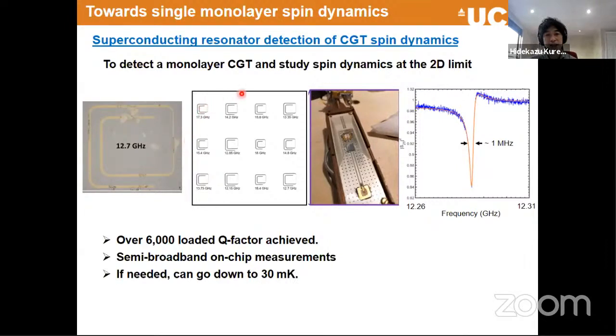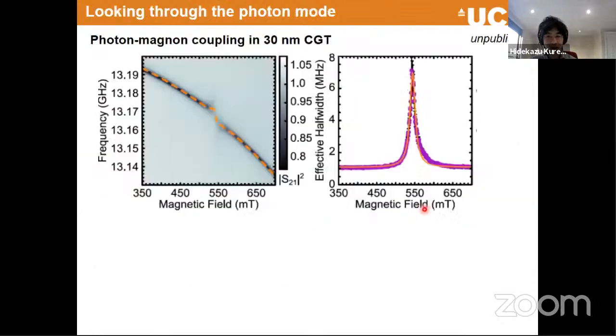Then we make it on the substrate and connect it to a transmission line, and then we can see the resonance. The loaded resonance, or Q factor, is about 6,000, so the line width is about a few megahertz at a resonance of around 12 gigahertz. So it's a reasonably good resonator if you consider it an on-chip resonator. Right, so I can show you this particular result.